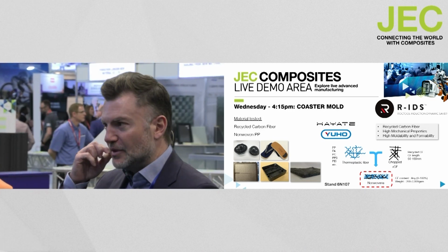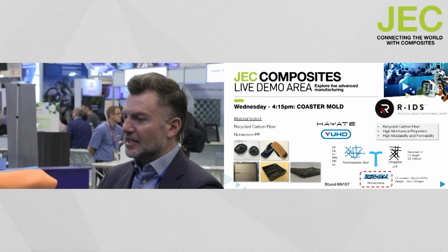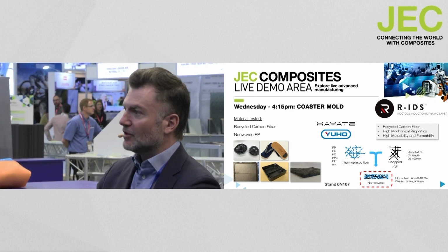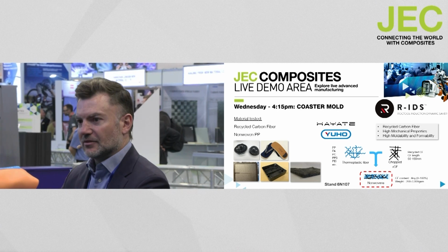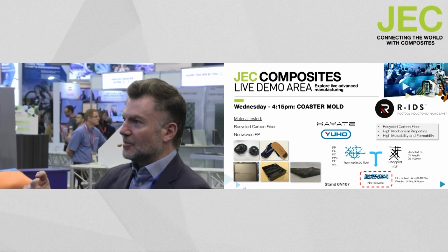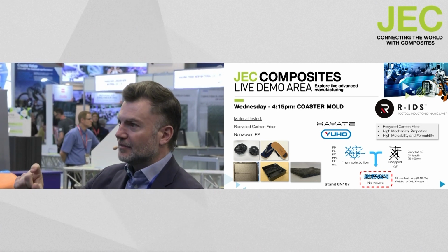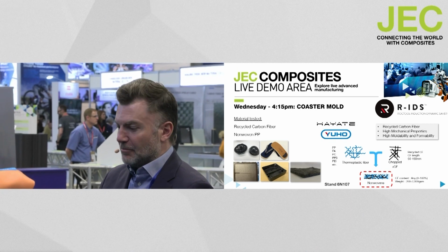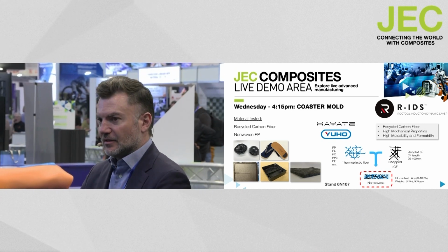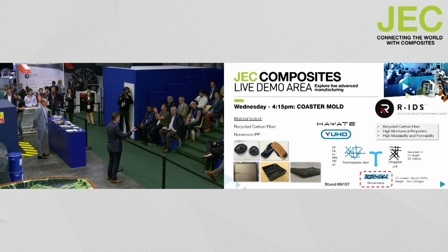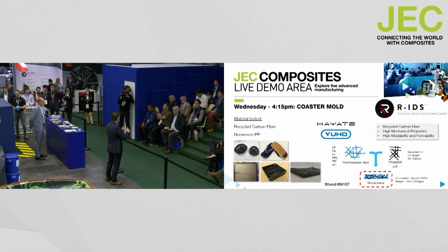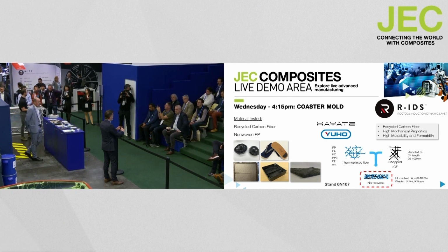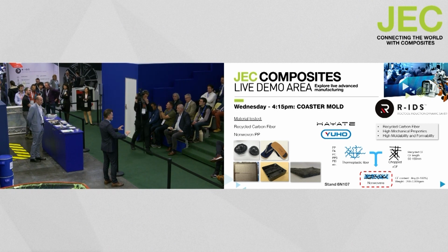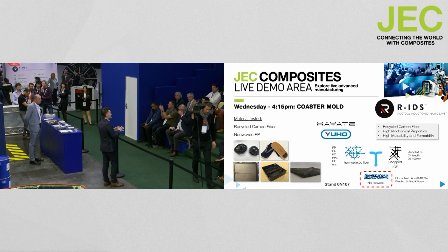So if we were in production, we would keep the heat platen at some level of temperature in between cycles, because the insert on top of it is being cooled down by itself, so it gives you the speed. But then in between, we just need a little bit more power to get back to the temperature to be molding. So the energy consumption in between the two steps is very low. It's 5 to 10 kilowatts to keep the heat platen in temperature.